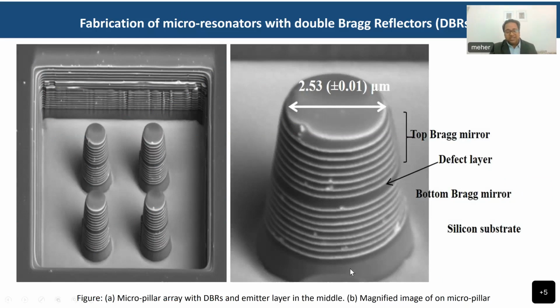These are the DBR, distributed Bragg reflector kind of geometries. You can see this is around 2.5 microns only. These are different kinds of materials, silicon dioxide and titanium oxide. This is a multi-layered structure, layer by layer. These were deposited by the dip coating method, around 400 nanometers each, and there are 20 silicon dioxide and 20 titanium dioxide layers.